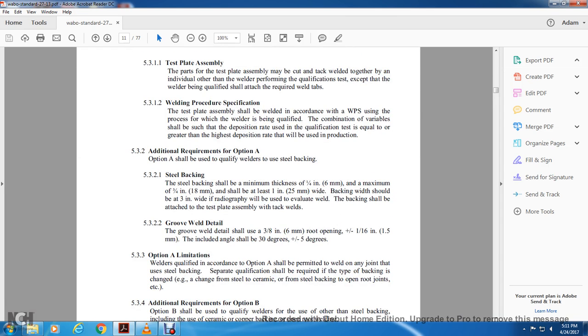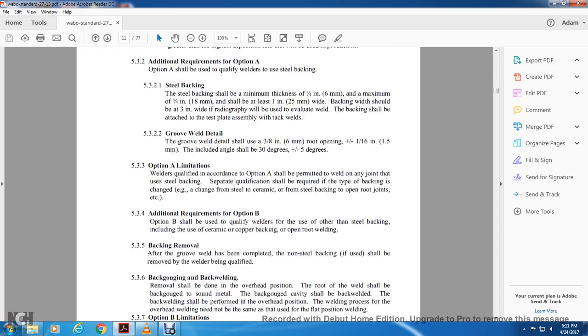5.3 Additional requirements for Option A. Option A shall be used for qualifying welders with the use of steel backing. Steel backing shall be a minimum thickness of 1/4 inch, 6 millimeters, and a maximum of 3/4 inch, 18 millimeters, and shall be at least 1 inch wide. Backing width should be 3 inches wide if radiographic testing should be used to evaluate the weld. Backing should be attached to the test plate assembly with tack welds. Groove weld detail. The groove weld detail shown shall be 3/8 of an inch, or 6 millimeters, root opening, plus or minus 1/16 of an inch, or 1.5 millimeters. This includes the groove angle, which shall be 30 degrees, plus or minus 5 degrees.